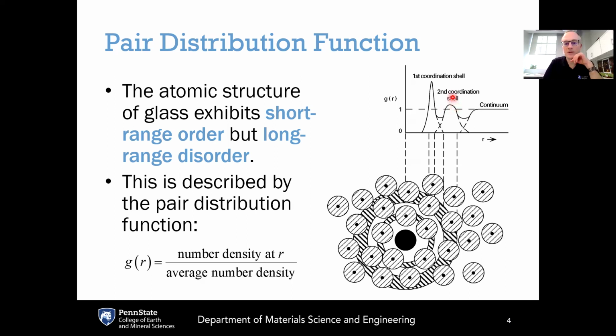That also gets reflected in the fact that the peak position here is quite a bit lower compared to the peak position for the first coordination shell. So again, this is indicating that we still have some order at the second nearest neighbor level, but there's less order compared to the first nearest neighbor.